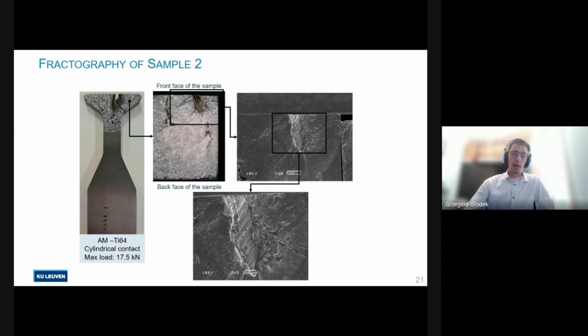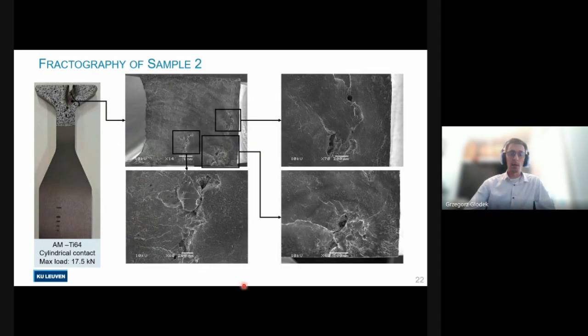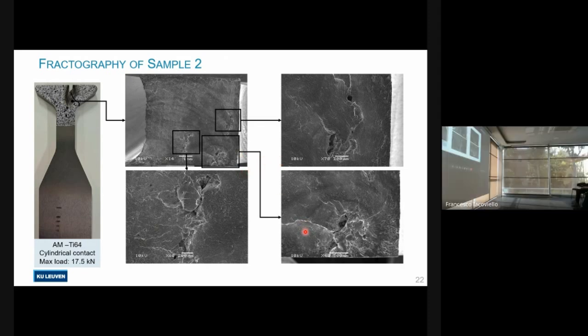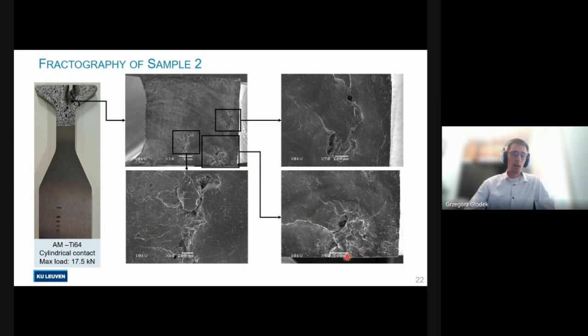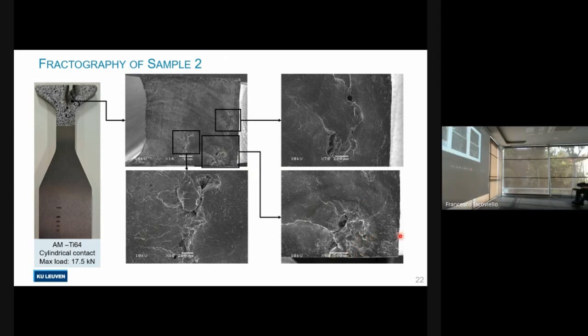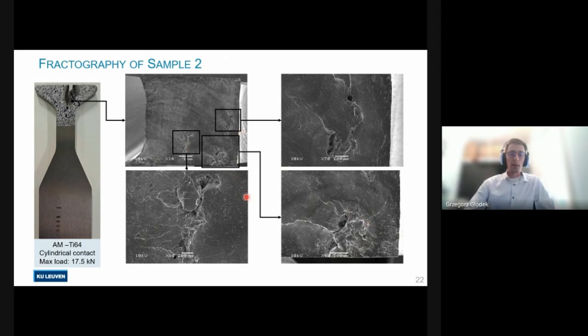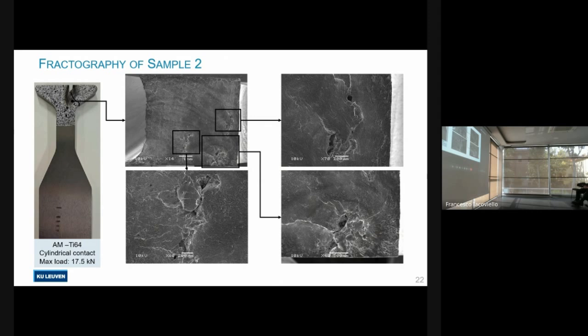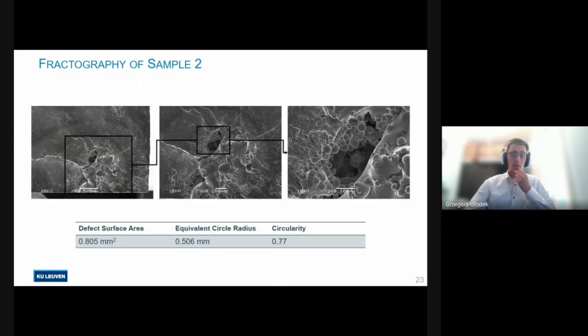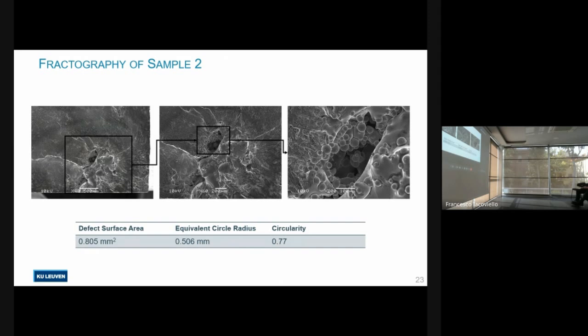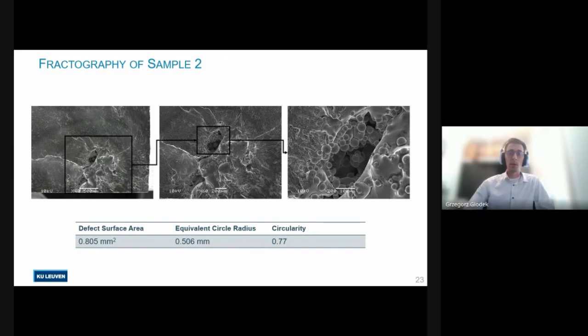If we look at the other side of the surface, we can see the other defects more clearly. Here, likely the crack initiated here and quickly propagated to the edge of the sample and also to the other defects, resulting in a rapid failure of the specimen. Now, higher magnification pictures of the critical defect show more of the not fully melted globular particles and highlight just how deep the defect is. It reaches multiple layers into the material.